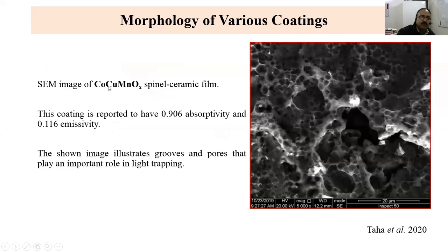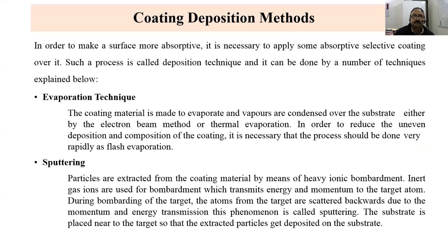Now SEM image of cobalt copper manganese oxide spinel ceramic film. This coating is reported to have 0.906 absorptivity and 0.116 emissivity. The shown image illustrates grooves and pores that play an important role in light trapping. So accordingly, you will see that all these things will tell us what is the reliability and how the coating will perform when put under different temperature conditions. Now, coating deposition methods.